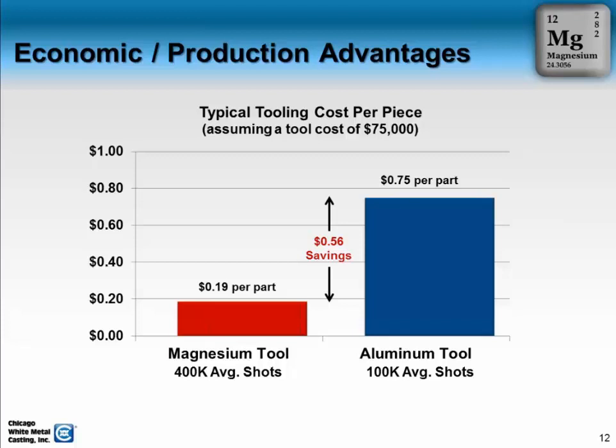On the column on the right, if we assume, as it shows on the top, a tool cost of about $75,000, which is maybe on the high side of a lot of die cast applications, but we just use it for reference. The column on the right shows the average tool shots that you can get out of an aluminum tool made for aluminum die casting, where you get about 100,000 average shots before some significant replacement or refurbishment needs to be done. So if you amortize the $75,000 tool price over 100,000 shots, obviously that's a 75 cents per part cost over the life of that tool.